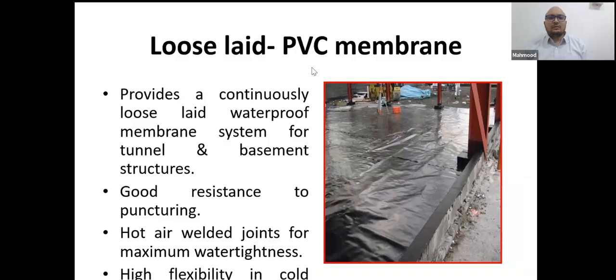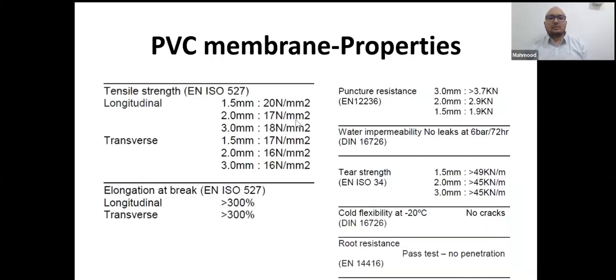PVC membrane is used as a loose laid waterproof membrane because of its good resistance to puncture, and it can be hot welded according to the dimension required on the site. Highly flexible, and you can see there is no water permeability, it is root resistant, and elongation at break is 300%.